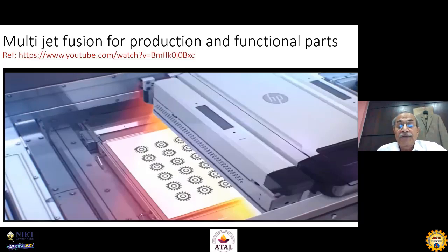Typically, let's say if we are printing in nylon, the temperature of the nylon is raised to about 140 degrees. Then the spread of ink happens. Then you increase the power of the same fusing lamp because this is a heat absorbing ink. The places where the ink has been spread, the temperature goes to about 165, 170 degrees, and at 170 degrees, the nylon melts. Therefore, you have been able to create a fusion with the previous layer rather than adhesion on the previous layer. And since the fusion is happening, your part becomes very, very strong. The speed at which the printing can be done is much better, and the reliability is much better. Let me show you how this works.